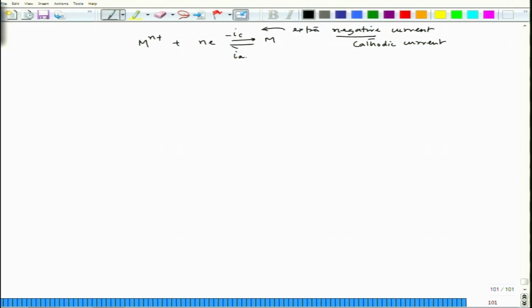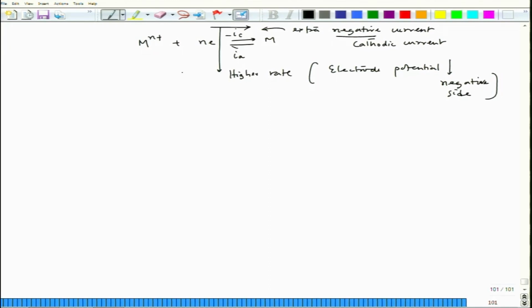Then this reaction would happen at a higher rate. If it happens at a higher rate, that means this reduction process happens at a higher rate. In order to maintain that reduction current density, the electrode potential would switch to the negative side. Why negative side? Because when it switches to the negative side, this metal surface is becoming more and more negative, and that is why the supply of electrons to this reduction process would become easy. Then its potential becomes, let us say, E 1.